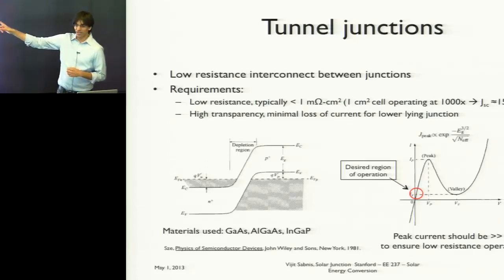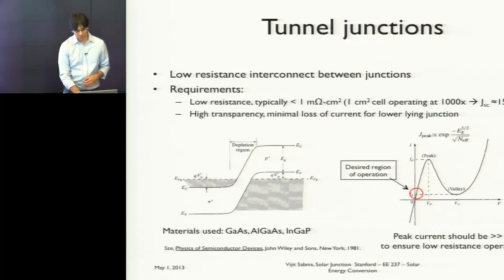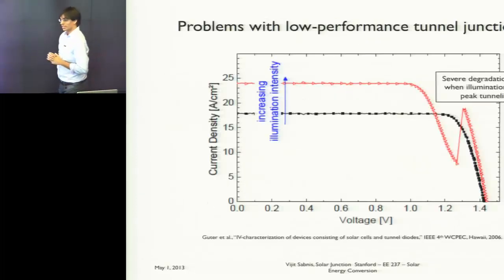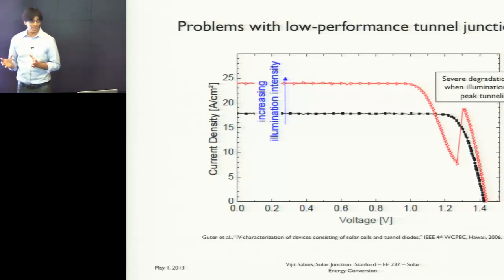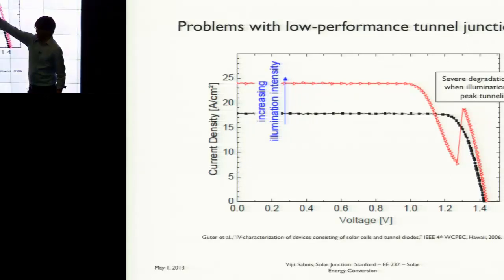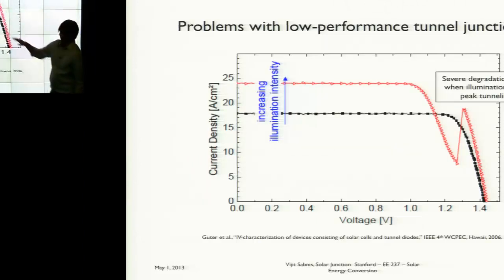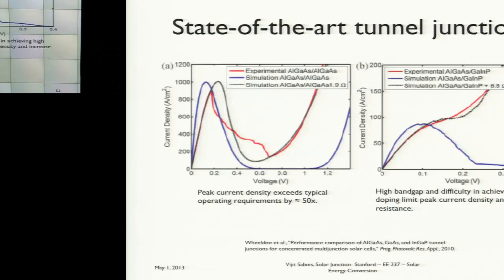Now, these tunnel diodes are very difficult to grow. They're actually a big problem, and what people found in the industry early on, when there was still a lot of engineering development needed to make tunnel diodes, is that if your Esaki peak, the tunneling peak current density, is lower than your short circuit current, when you trace an IV curve outside, you end up getting this kink in your IV curve. We've actually made bad tunnel diodes which show this. If this ever happens in the field under real operation, you can imagine what your fill factor is. In this case, it's like 40% or something like that. So the amount of power out of your solar cell is rapidly degraded. These days, however, people have made tunnel junctions that have peak tunneling current densities that are much, much higher.